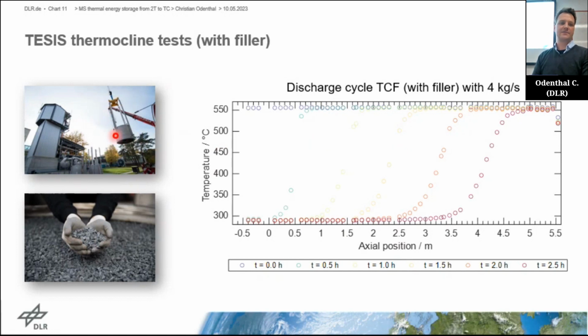There are in total 3 baskets, which can be stacked on top of each other. In this case, we tested basalt rocks with a mean diameter of roughly 1 centimeter. You can see that here in the picture. There we could successfully test this thermocline concept with the filler material. You can see from the difference to the pure thermocline that there's also some heat transfer going on between the salt and the solid material. That is also increasing the width of your thermocline region, basically this transitional region between the hot and the cold salt.